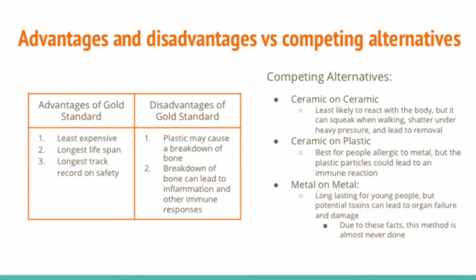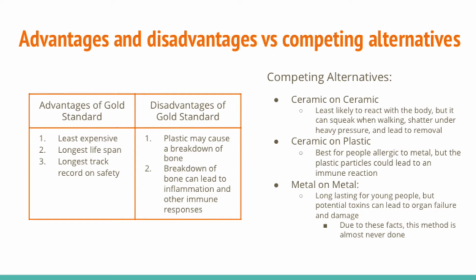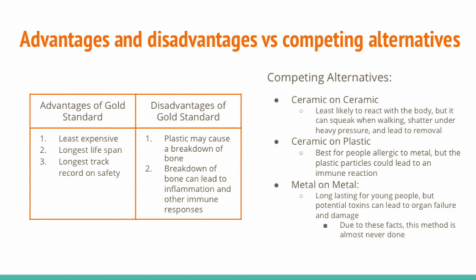However, there are some competing alternatives, such as ceramic on ceramic. It's the least likely to react with the body, but it can squeak when walking, shatter under heavy pressure, and lead to the necessary removal. There is also ceramic on plastic, which is best for people allergic to metal, but the plastic particles could lead to an immune reaction and inflammation. Finally, there is metal on metal, which is the longest lasting for young people, but potential toxins can lead to organ failure, damage, and death. So due to these facts, this method is almost never used.